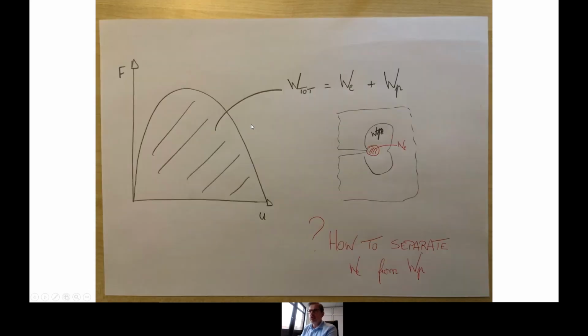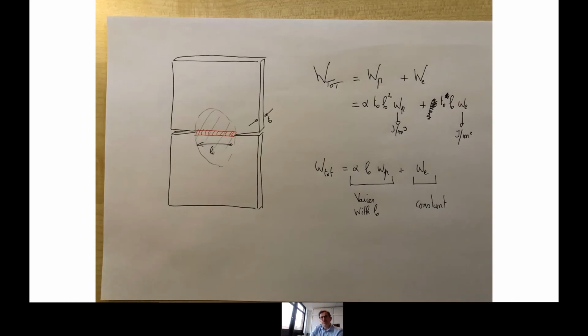All right, so for the essential work of fracture, the question is how to separate the work spent in the plastic zone and the work spent in the fracture process zone. The beauty of the approach is that, based on dimensional reasoning, you express the total work, W tot, as the sum of the work of the remote plasticity and the work spent in the fracture process zone while the crack is propagating throughout the entire ligament. Fortunately, based on dimensional consideration, the plastic zone work depends on the ligament length, and not the essential part, when you normalize the total work by the ligament cross-section area. That's the way you can separate the two terms and get access to the essential work of fracture.